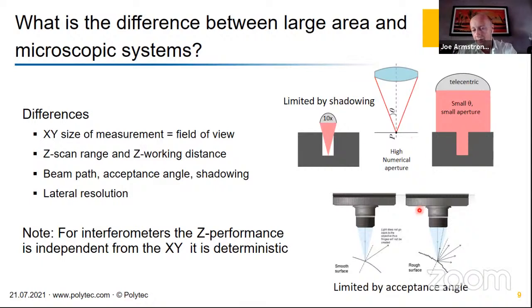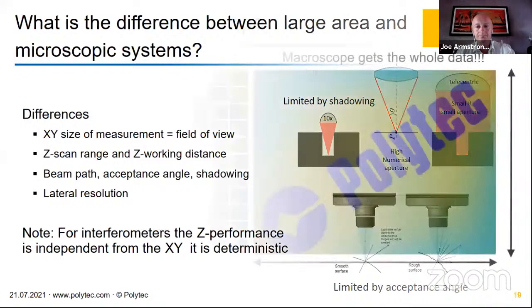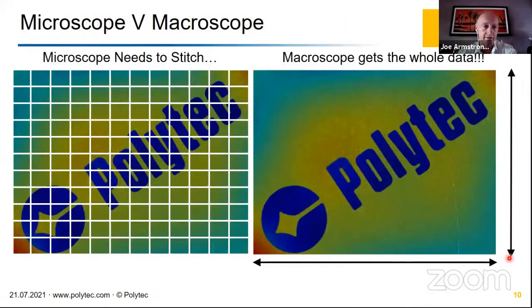For both instrument types, you then have to look at the numerical aperture, you have to look at the slope handling ability of your lens system, but you can go beyond mirrored surfaces, providing you get some localized scattering on a surface. You can achieve quite good slope handling ability. With a macro lens, you can measure maybe 65 degrees. With the microscope, I've even measured surfaces up to 80 degrees. So the performance, if a surface is compliant, can be surprisingly good. And that's pretty much the same for all optical systems.